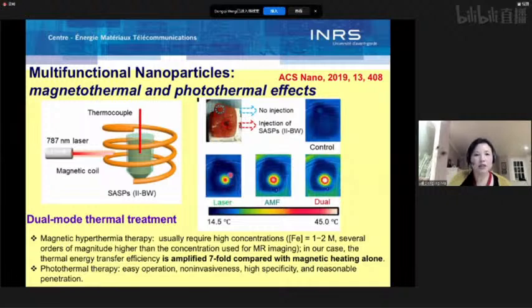And then we observe the temperature increase. We can see that with the laser applied, temperature increases, and with the magnetic field applied, temperature increases further. If we combine both, the temperature quickly increases to about 45 degrees in a few minutes. As a contrast, for the part without injection of multifunctional particles, we don't see any temperature increase. So this study shows that by combining magnetic materials and luminescent material together, we can realize magnetothermal and photothermal